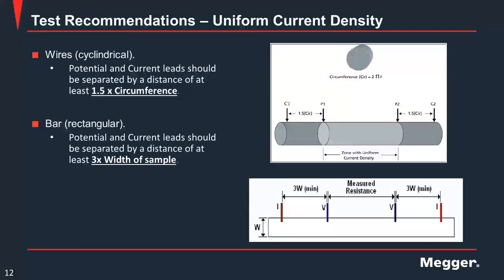The first one is if you have a wire, or maybe the test specimen is a wire type with a cylindrical shape, you need to make the potential and current leads separated by a distance of at least 1.5 times the circumference. You can see on the right side of the screen, if the test specimen is like this, a circle wire or cable, you need to put the position of the current and potential probe at least 1.5 times the circumference, where the circumference has the formula 2 multiplied by pi by r.